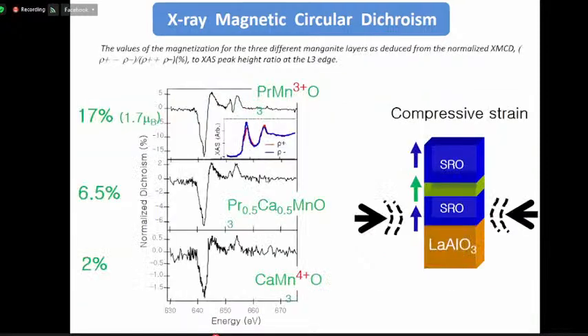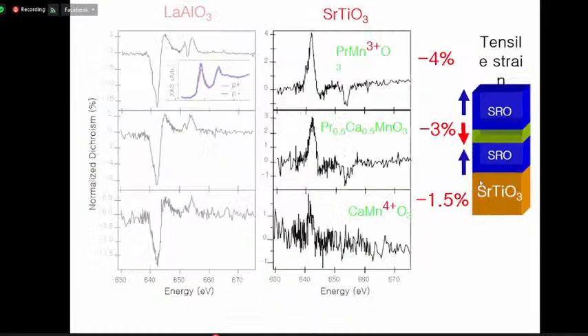From this, we see the manganite is insulating and antiferromagnetic. It has upward magnetization in the case of the LAO substrate, but in the strontium titanium oxide substrate case, the spin direction is opposite compared to before.